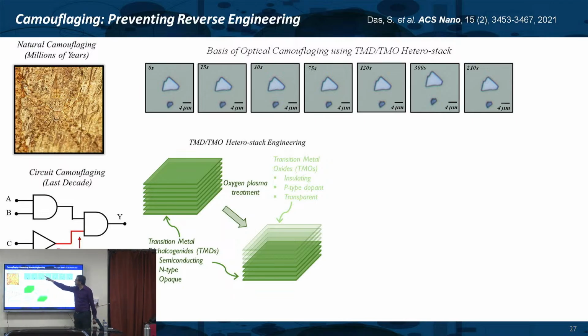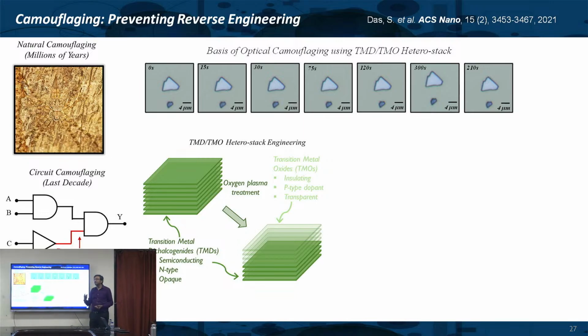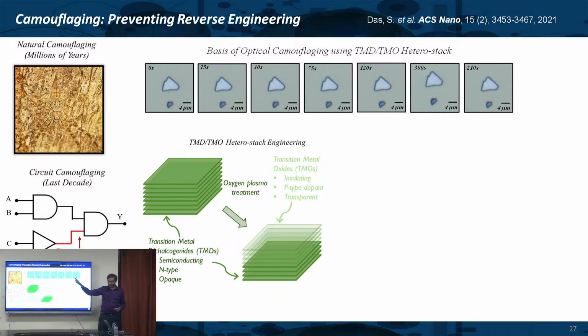So what am I doing? You see 15 seconds, 30 seconds. Remember this timestamp? We are literally doing oxygen plasma. On top of it now there is an oxide layer which is transparent, so the optical appearance of the flake does not change. But now this material which is on the top converts the bottom material into p-type. It just dopes it, this surface charge transfer doping that we spoke about. So although we started with an n-type material, it has become a p-type material because of this unique property of 2D material, where the oxide is number 1 transparent and number 2 serves as a p-type dopant for the underlying material. So I have now camouflaged the function of the material without changing its appearance.